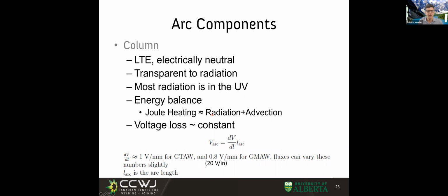The voltage loss in the arc column is one of those things that is convenient. It didn't have to be like this, but it is like this. And it's more or less 1 volt per millimeter for the TIG arc, and more or less 0.8 volts per millimeter for MIG, right? These numbers, right now, I cannot give you a derivation and I cannot give you lots of specific experiments, but there's agreement in the community that these numbers are more or less right. So right now, you would know this, that if you have a 5 millimeter arc in TIG, you have at least 5 volts in the column alone. And if you increase the arc in TIG to be 6 millimeters, then you would have increased 1 volt in that arc.